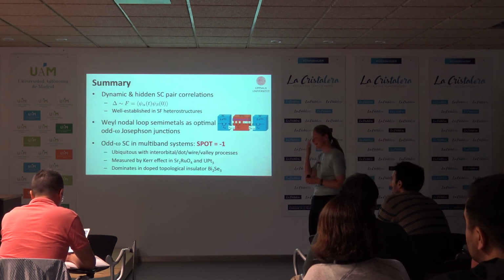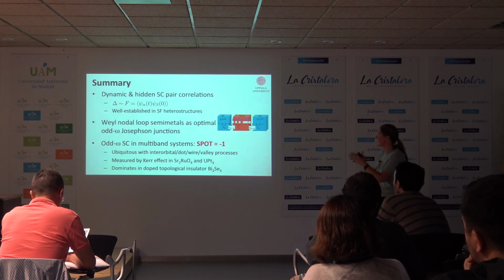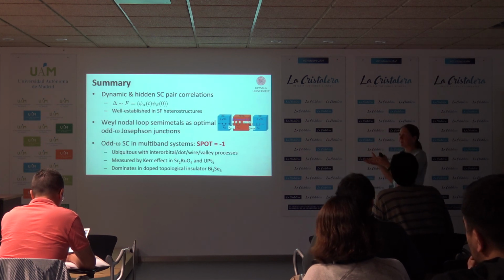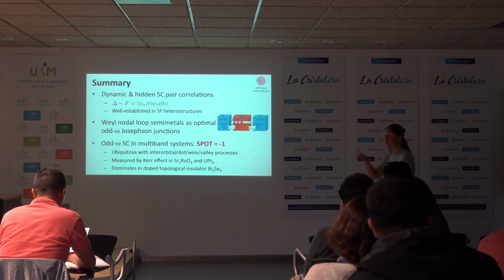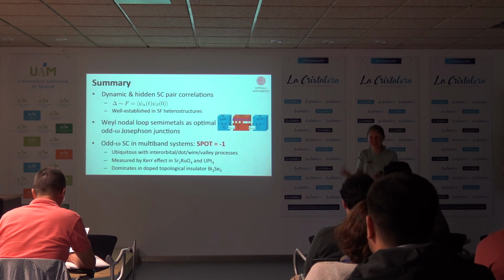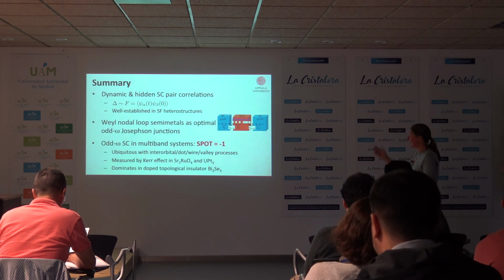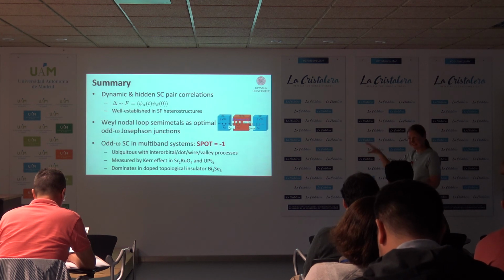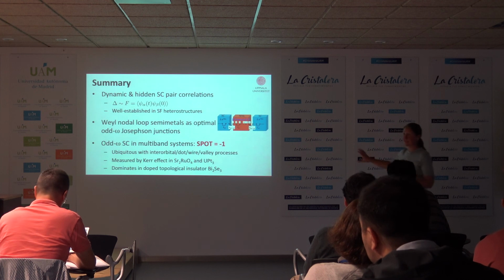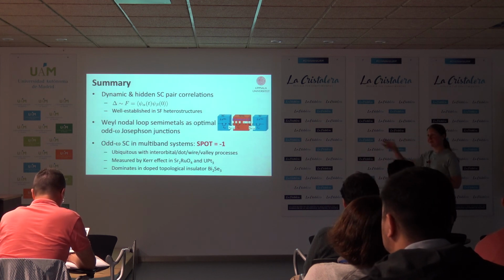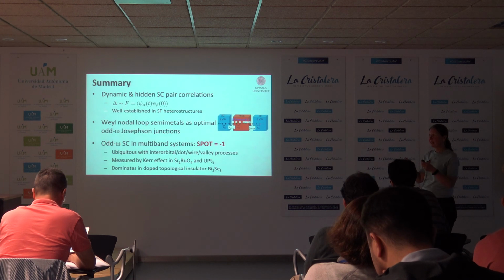Yeah, so when you first come up with this, it's a simple two-orbital model, and it works in a theory game, but can we find it? So we started looking around at what multi-orbital or multiband systems there are. In Sr2RuO4, if you believe in the intrinsic Kerr effect, it has to happen there, that you have a little bit of this interorbital process. If you believe in the nematic state in bismuth selenide, the only pairing consistent with group theory is odd interorbital pairing. So I think I agree with you.